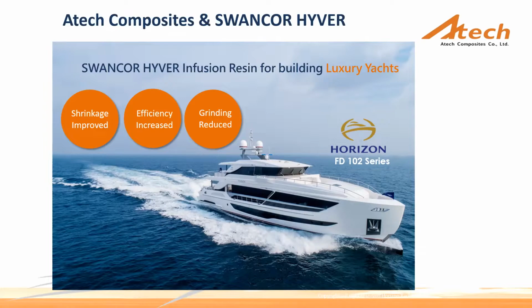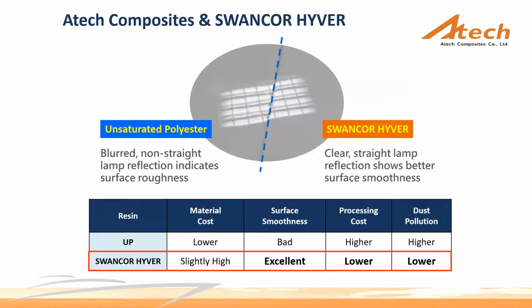But the severe shrinkage caused by the chemical reaction from a huge amount of unsaturated polyester resin is a big issue for us. It will cause a phenomenon we hate to see: print through, or pattern through. Print through or pattern through is when the fiber pattern or the foam core grooving pattern appears on the gel coat surface. Generally, we can check it under the light and just move your head to see the pattern. Let's take a look at the photos in this slide.